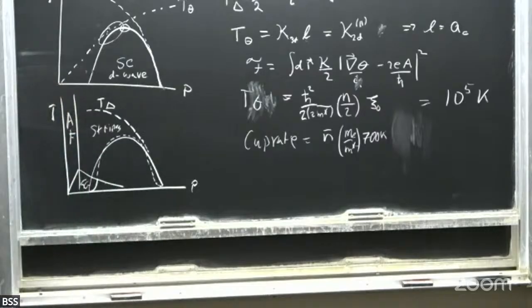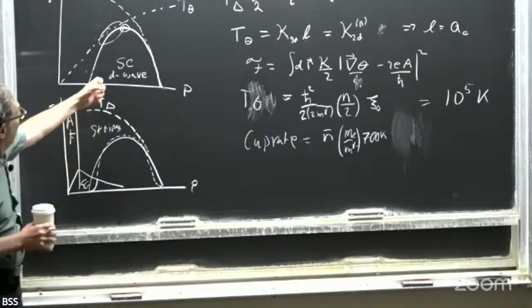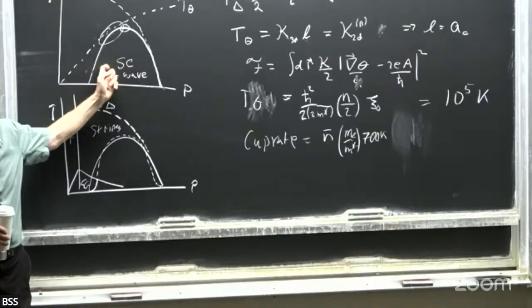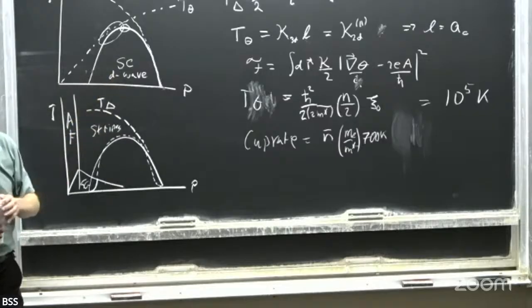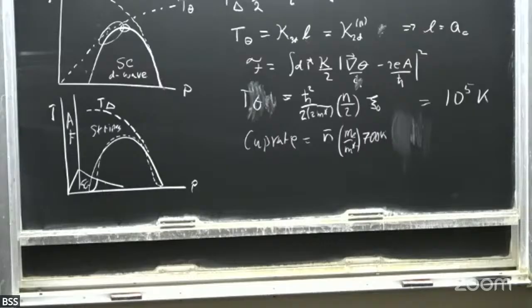But it's within this approach, it's liquid, but just in a strongly different regime than like the weak. So you have to be a little bit careful about your definition. So here, of course, there's not a Fermi liquid because it's a superconductor. Okay, so if I suppress superconductivity with a field, you've gone through 2 phase transitions. So it turns out you've, of course, suppressed superconductivity. Also, it turns out that in these materials where they see the quantum oscillations, there's a field-induced charge density wave transition. So you do see quantum oscillations. They're very clearly Fermi liquid-like, but they're across 2 phase boundaries from what I'm looking at.